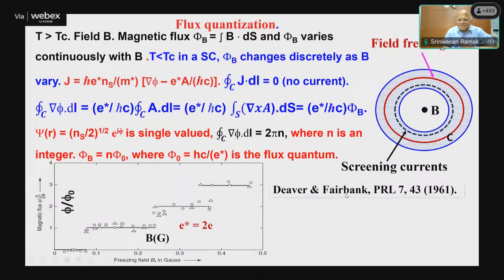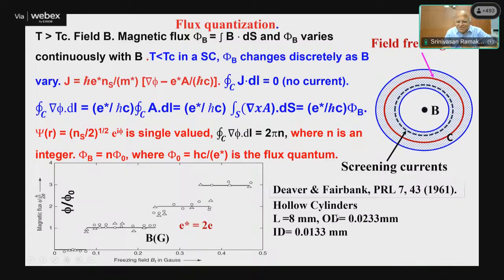Okay. So this experiment was done by Doll and Näbauer and by Deaver and Fairbank later, in 1961. They showed this in hollow cylinders. These are really miniature cylinders, 8 millimeter length. The OD is 23 micron. The ID is 13 micron. Extremely small cylinders, because only then can we measure this jump.